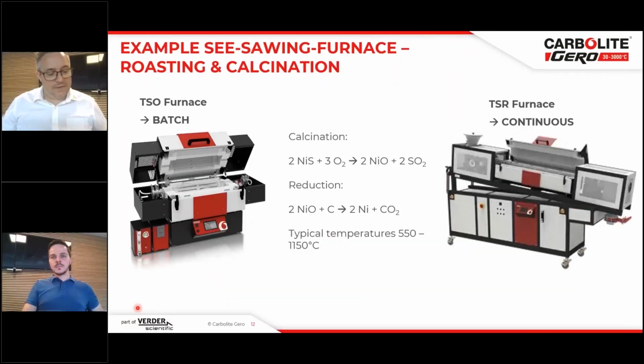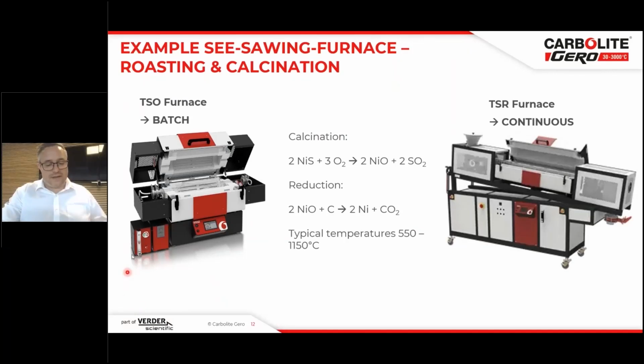Okay, so in this example, we have a seesaw furnace arrangement where the process cycles between two process steps. So that's the roasting and the calcination. So the nickel sulfide is oxidized with air in the calcination phase to give us nickel oxide and sulfur dioxide. In the reduction phase, the nickel oxide is reduced with the coke to raw nickel. And as a batch system, the TSO, which is the furnace you see on the left-hand side of the screen now, would allow the material to be mixed.